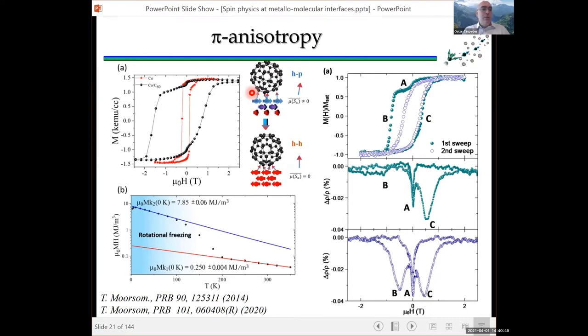So what you are seeing here is not an exchange bias. What you are seeing here is a reversal where the magnetic field first rotates the molecule. And that's why you need a very large magnetic field to do it. And once the molecule is rotated and the electrical dipole is destroyed, then the coercivity is much smaller. And then it remains smaller for all the consecutive loops that you measure.